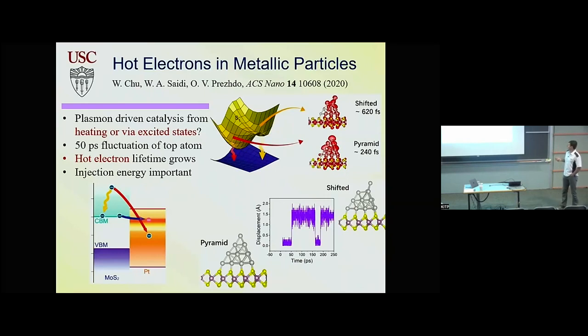And we talk about charge transport between the two materials, and then the lifetime of the excited state in the metallic cluster. So what we see on the time scale of maybe 100 picoseconds or so, we have this oscillation. There's a structural evolution of the edge, or in this case, the apex of the quantum dot, that changes the electronic properties. And the lifetime of the special state that's localized, when you have the top atom detached from the rest of the pyramid, becomes longer. The difference is maybe just a factor of 3, but this could be quite important for chemistry, because when you have a bond, vibration of a bond is maybe 100 femtoseconds, and when you need to break this bond, if you have an excited state that lives for 600 versus 200 femtoseconds, it can matter.